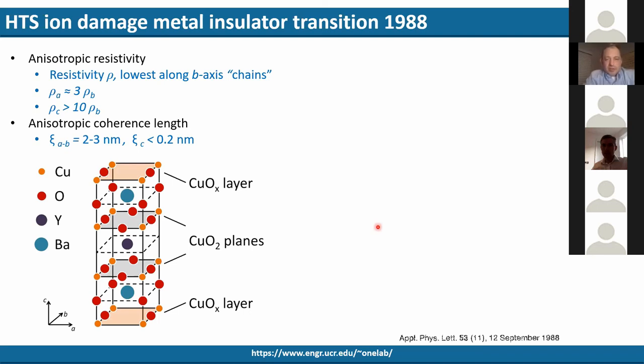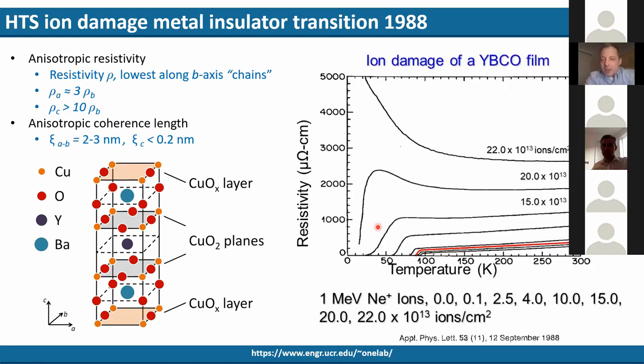And the way that we make our Josephson junctions, we kind of exploit something that's usually detrimental. Early on, when HTS just kind of hit the scene, both Bell Laboratories and IBM was working on experiments where they ion-damaged the YBCO or an HTS film and put some disorder in it. And when they put that disorder in, what they saw is when you looked at the resistivity as a function of temperature for a YBCO film that was irradiated subsequently with different doses. Here, they used 1 MeV neon ions, but it worked similarly with other ions, and other people done these experiments in Europe and Cambridge.